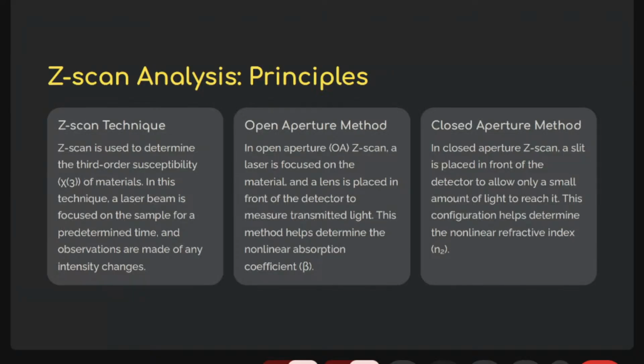There are two methods. One is the open aperture method, another is the closed aperture method. In case of open aperture, a pulse laser is focused on the material, and we put a lens in front of the detector to determine the transmitted light. From open aperture, we can get the nonlinear absorption coefficient. In closed aperture, a slit is introduced in front of the detector to allow only a small amount of light to reach the detector. This configuration helps to determine the nonlinear refractive index.